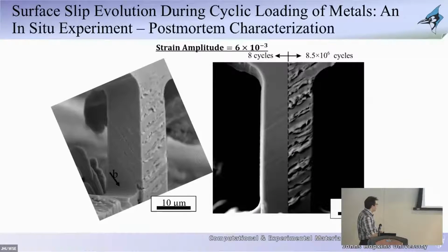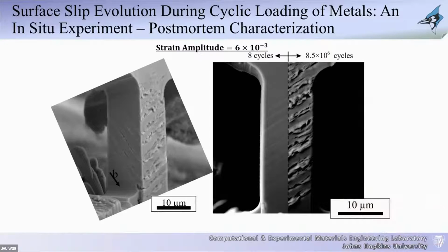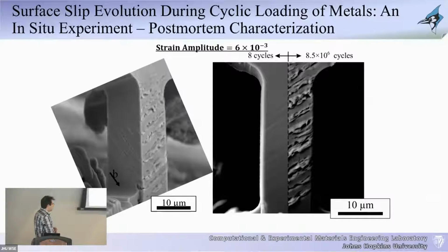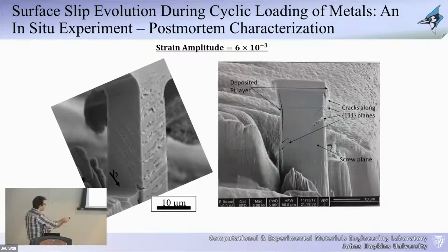And just to show you what the sample looks like after deformation. So this is a 3D view of that same sample. And this is basically the sample after 8 cycles versus after 8 million cycles. And you can clearly see that each one of those precursor slip events happened on the surface. The sample was initially flat. There were no apparent slip bands forming on it. After 8 cycles, you start forming them, and then they stabilize for a while as the material continuously hardens, and then eventually all these slip traces form on the sample, and each one of them is actually associated with interior